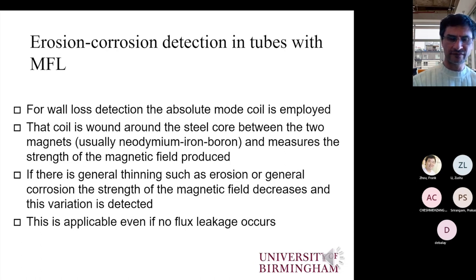Of course, there is the alternative that employs DC magnets or DC electromagnets in the place of the rare earth magnets, but this usually results in a bulkier probe, which also requires that the DC coil that generates the electromagnetic field is energized somehow. So that is an additional problem that we have to address during the inspection.